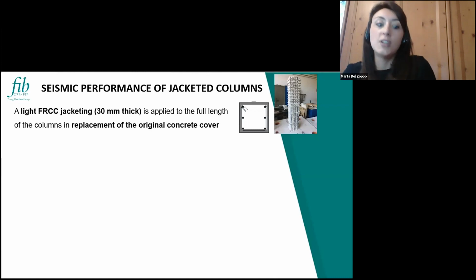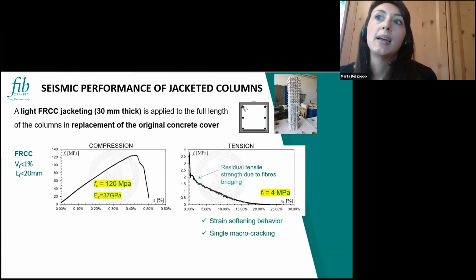So after this general overview about the use of fibre reinforced cementitious composites as a strengthening technique, we will now see in detail how the jacketed columns will perform during seismic actions. For this application, I'm adopting a 30 mm thick layer of fibre reinforced cementitious composite with a strain softening behavior. And this material is applied for the full length of the columns in replacement of the original cover, with a very slight cross-section enlargement. The columns that we are analyzing are made with a poor quality concrete with an average compressive strength of about 15 megapascal.